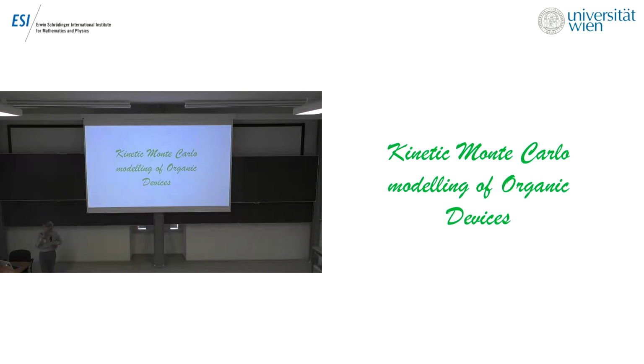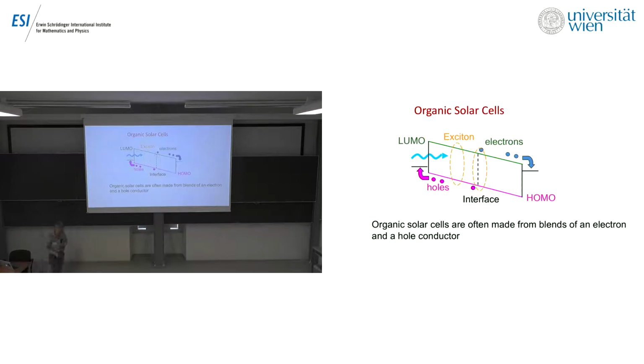So now I want to move on to organic devices, which Frank introduced in his very nice talk yesterday. So for those of you who don't know how organic solar cells work, you excite your electron and hole across the band gap, as you would with any inorganic semiconductor, but they form excitons. The excitons are very tightly bound in this case, bound by half an electron volt.